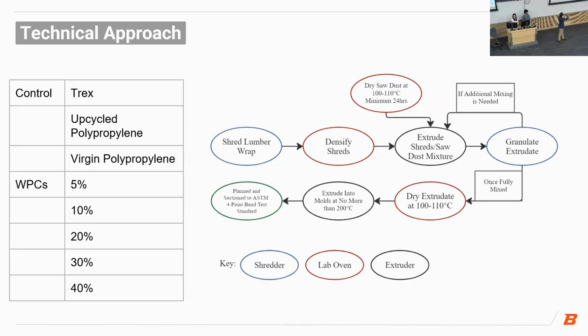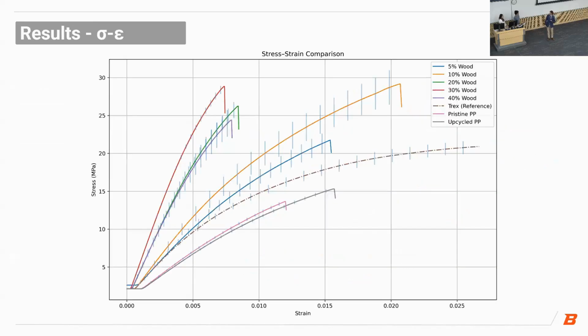The specific process that we used is we processed both the lumber wrap and the sawdust before feeding them into an extruder. We then granulated the extrudate and potentially repeated that process as needed to ensure complete mixing. Once they were fully mixed, we dried the extrudate one final time before feeding it into a final extrusion, where the 1x1 boards were then sectioned and planed according to ASTM standards for a 4-point bend test.